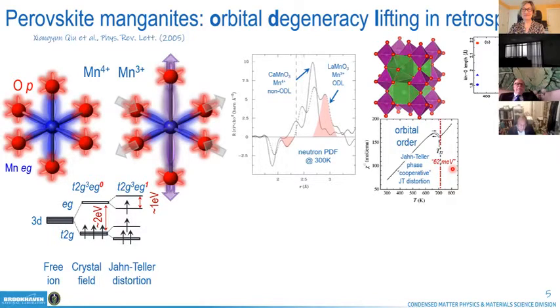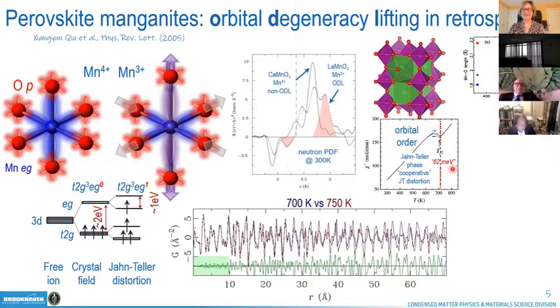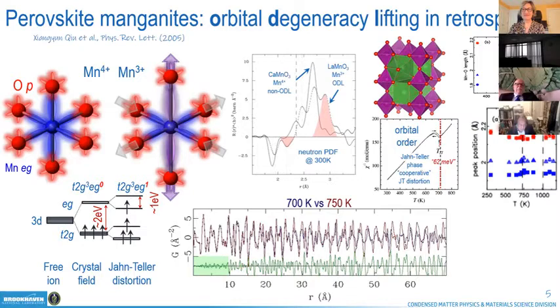Okay, so if you take a local view, you immediately see that basically this transition is of order-disorder type, and that the distortion locally persists. You can measure it, and you can basically see that the distortion that is responsible for lifting this degeneracy does not really care about the transition.